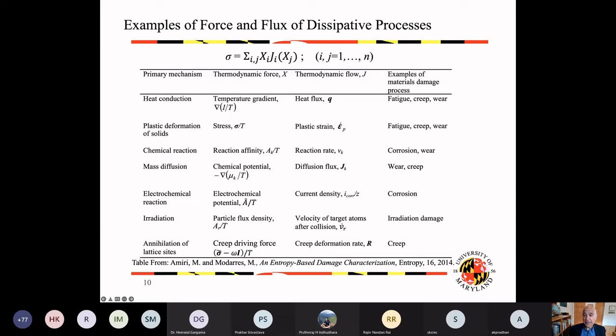We can easily describe fatigue, creep, and wear, where these elements of heat conduction can be measured. We have plastic deformation, such as stress and strain, which in, let's say, fatigue and creep and wear, we can find them and measure them easily, and therefore dissipated energy can be found. I won't go through all of them, but again, in this paper in the past, in the journal Entropy, it has been defined what these forces and fluxes in reliability are that cause the damage.